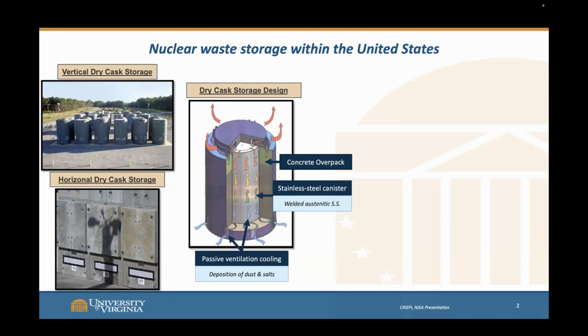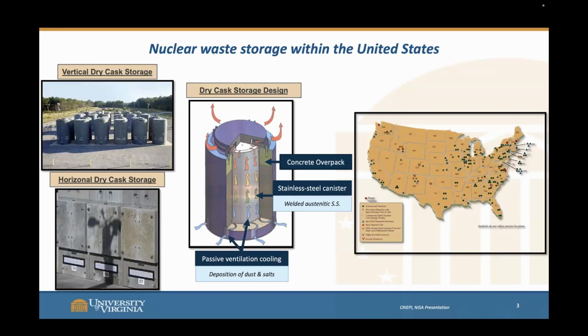For storage in the United States, there's 2 different ways. There's vertical dry cask storage, and there's also horizontal cask storage. And when it comes to these cask storage systems, it is stainless steel canisters, specifically welded austenitic stainless steels that are placed into a concrete overpack. And then there's vents on the top and bottom and air space in between that stainless steel and that concrete that allows ventilation so that the canister is staying cooled. But this also then allows the deposition of outside constituents, particles and salts to be formed on that stainless steel canister surface.